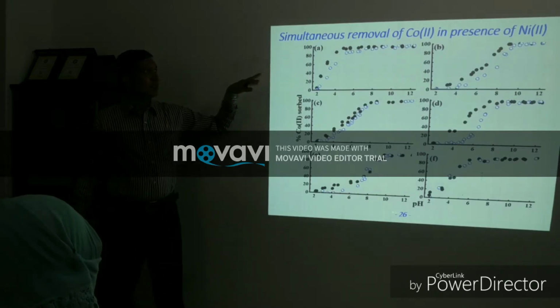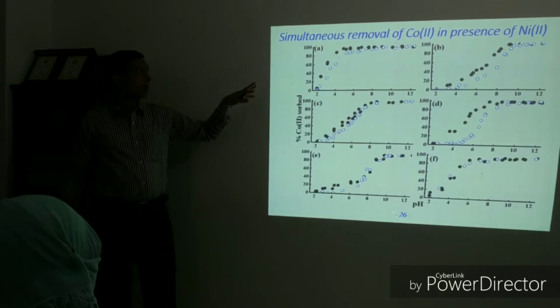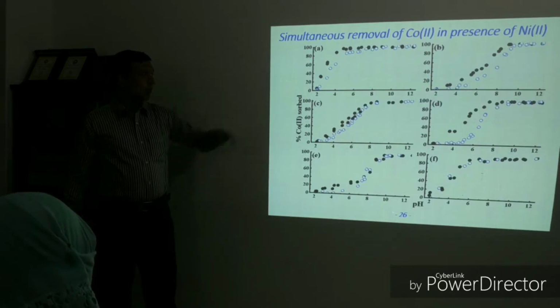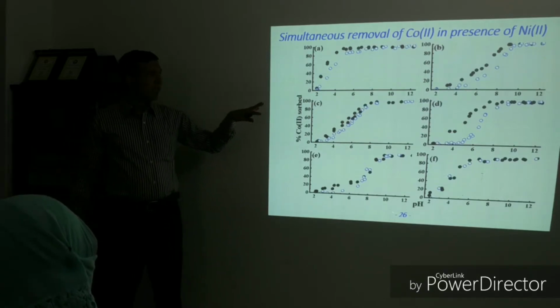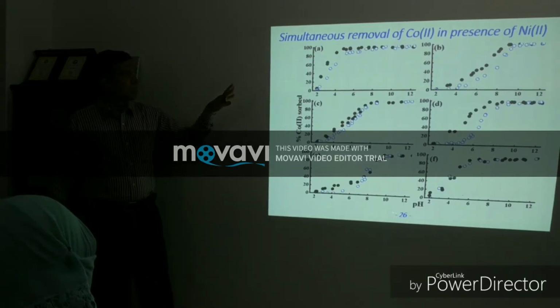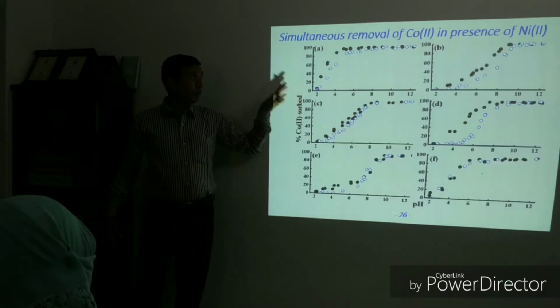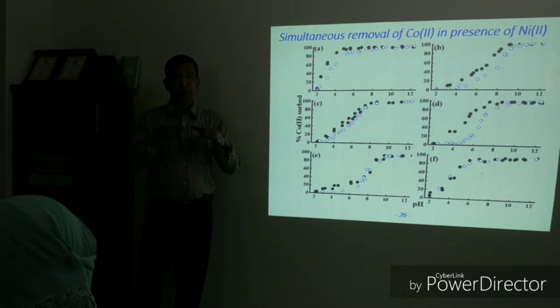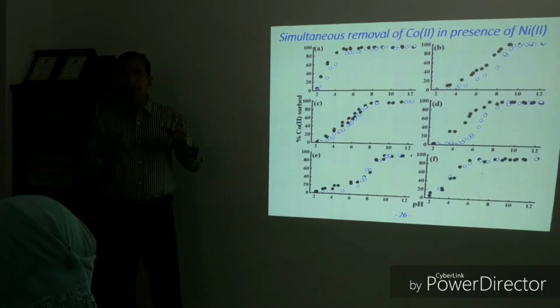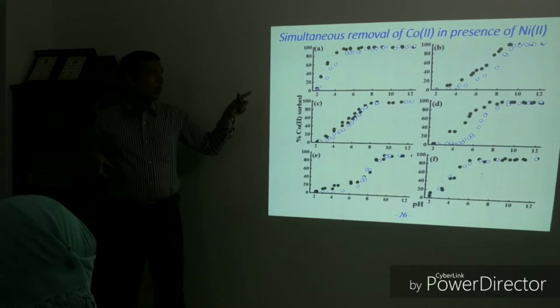So the open circle indicates the simultaneous removal, while the closed circle indicates individual cobalt removal. From this we see that in almost all cases the presence of nickel decreases the amount of cobalt adsorbed. This is due to the competition of both metal ions for a finite or limited number of surface sites.